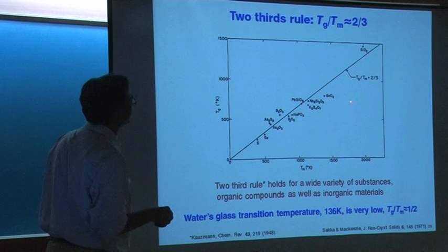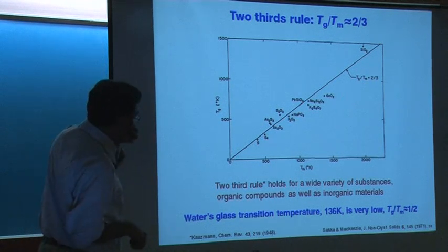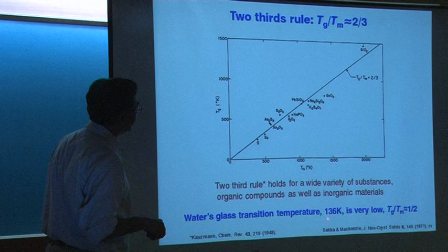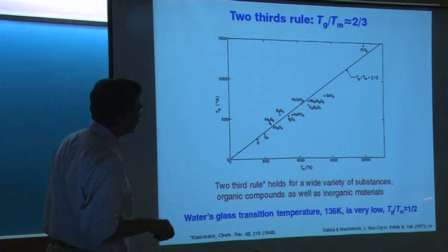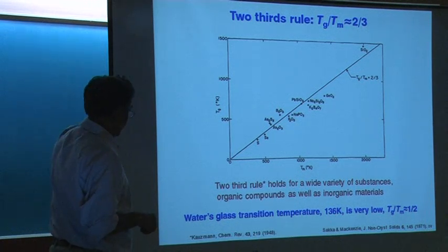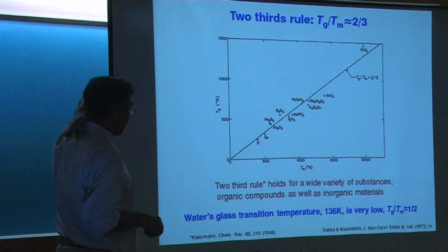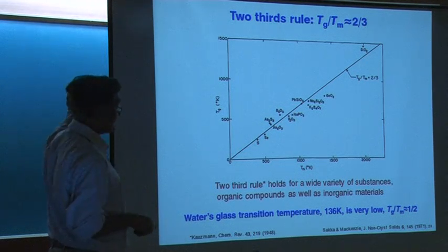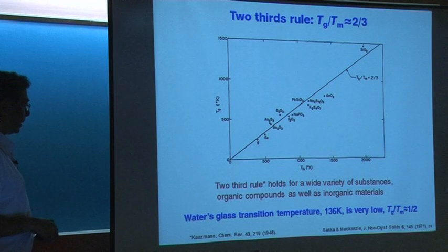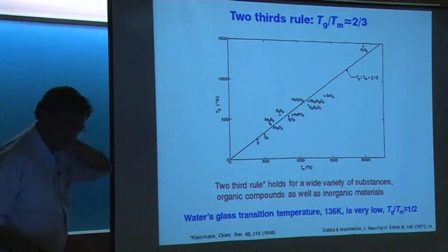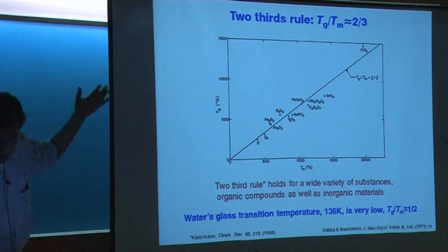Water completely deviates from that. Water you cannot put on the graph. Water's glass transition is about half. So if water had followed this, 2/3 of 273, that means near 180 Kelvin, water would have undergone glass transition. It doesn't do so. It continues to remain liquid.